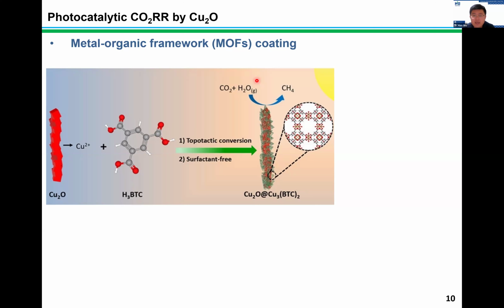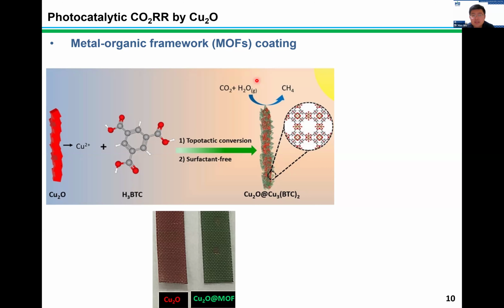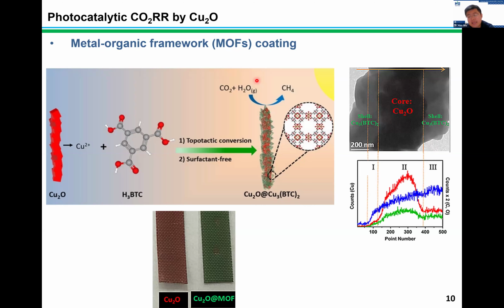By using this method, we can coat a very homogeneous layer of copper MOF on its surface. Here is the real image of the samples. Upon the topotactic conversion strategy, we change the original red color of cuprous oxide into a green color. This green color is reflected by the copper MOF upon absorbing water from the atmosphere. This color is very beautiful, just like a green leaf as we often think of from nature. And further, the TEM and the corresponding EDS results suggest that we have successfully synthesized the core-shell structure with cuprous oxide as the core and copper-based MOF as the shell.